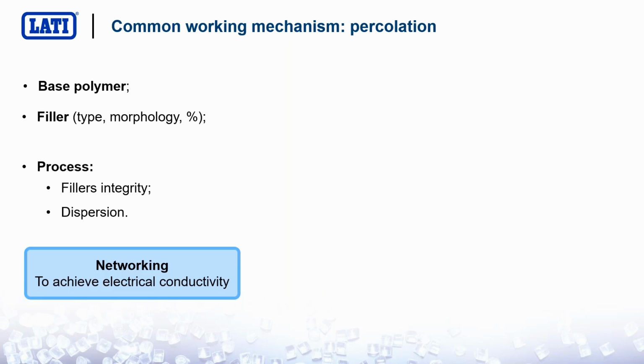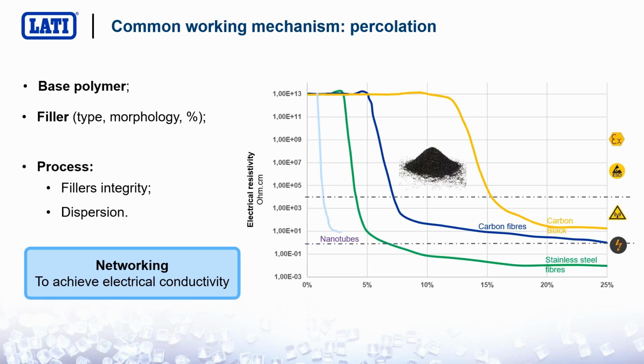The keyword is networking. You have to be able to create a conductive network in your injection molded part. And the result is here. You can actually see how this percolation threshold will lead your application to a perfectly conductive solution, depending on the kind of filler.